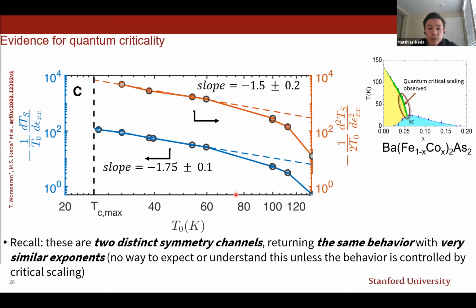Now, it's important to understand that these are two different symmetry channels that basically provide two completely different tuning parameters, maybe as different as magnetic field and pressure are. And it's really a very striking result to find the same slope here. And we interpret this as evidence for nematic quantum criticality in a wide regime in the phase diagram of cobalt-doped